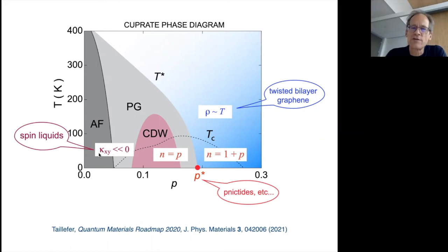Okay, very good question. It depends on the material, but the general thing we observe, our measurements all more or less start at 100 K and then we go down in temperature. So the signals that we see, whether in cuprates or in this copper telluride or even in ruthenium trichloride, the signal picks up as you cool below 100 K and maybe down to 50 K, typically it's linear in field. So you double the field, you double kappa xy.